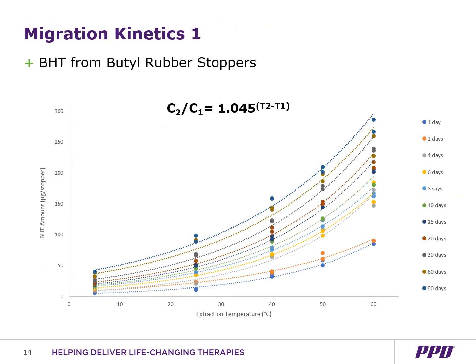From the data, we were able to develop a concentration projection model related to temperature. In this plot, we have BHT concentration plotted against extraction temperature as shown here, for a given time interval. Each set of data plotted, each curve, represents a given time interval in days. As the figure shows, the extracted BHT amount increased exponentially with extraction temperature.